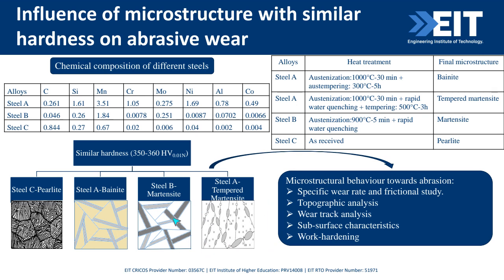These schematic representations show pearlite, bainite, martensite, and tempered martensite. In tempered martensite you have carbides in a ferritic matrix; in bainite the yellow regions are bainitic ferrite laths and gray regions are retained austenite; pearlite has a typical lamellar structure. All four were subjected to two-body abrasive wear followed by post-wear characterization — examining the worn surface and the subsurface beneath the worn area.